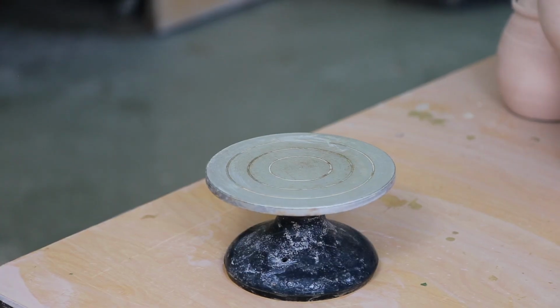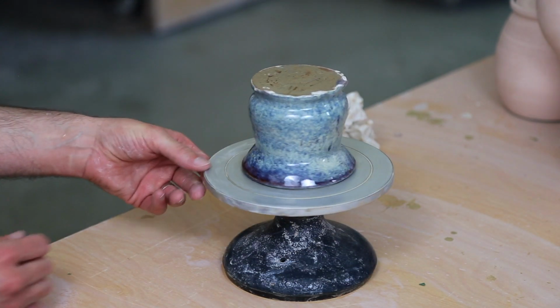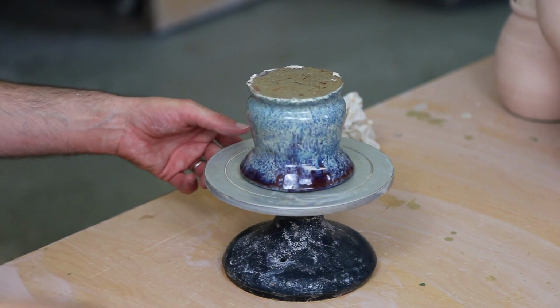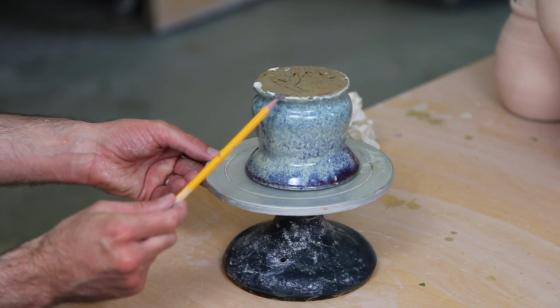So again, the basic premise of waxing is to repel glaze from the bottom of your pot so that the glaze doesn't fuse to your kiln shelves. Glazes do run and some fusion may be inevitable despite your best efforts waxing. This student didn't accommodate for this runny combo and didn't wax up high enough. Therefore, some of the kiln shelf is fused to her pot and even tore a small chunk of the base away when removing from the kiln.